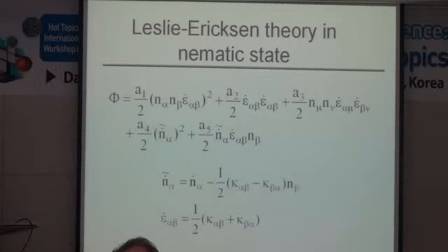That part becomes a bit involved. You can derive the expression for the energy dissipation function purely as Ericksen and Leslie did, by a purely symmetry argument. So it has to be a quadratic form in terms of n dot and the velocity gradient kappa, and also it has to satisfy some rotational invariance. So if you rotate the whole system with a constant angular velocity, the energy dissipation should not change. And with that requirement, you can show that the energy dissipation function is written in this form.